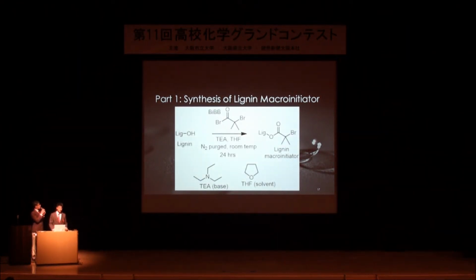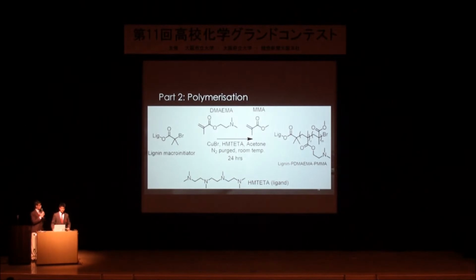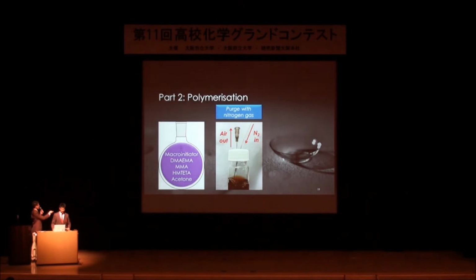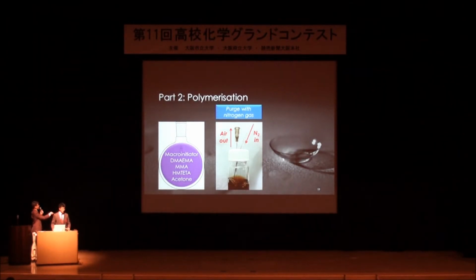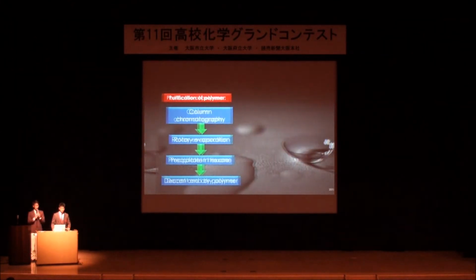So this is our synthesis. The first part essentially covers the addition of BiBB as seen in the structure on the screen. We also want to add all these reagents and stir it in the nitrogen atmosphere for 24 hours. The second part is the polymerization process. So what we want to do is to add the following reagents into reaction flasks and purge the nitrogen gas first. After that, CuBr will be added to kickstart the reaction, and this will be stirred for 24 hours in nitrogen. After which, we will work up the polymer.